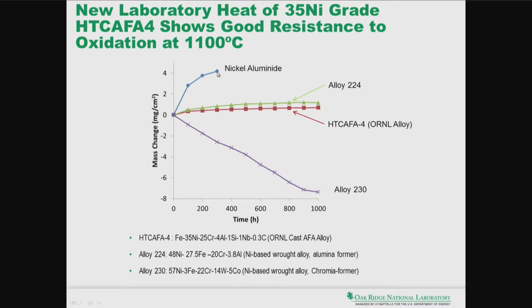And the nickel aluminides actually don't do as good as the alloy 224, which is, again, I just want to show you that it's got about 48 nickel and 3.8 aluminum and some iron and chromium, which is actually a nickel-based wrought alumina-forming alloy. And the HTCAFA-4, which is an ORNL cast AFA alloy, which is also an alumina-former. And you can see how these two are tracking each other very well up to about 1,000 hours.